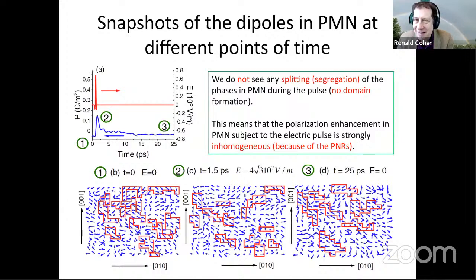Hi, Sergey. Nice talk. I wanted to ask you, your electric field is practically terahertz radiation. And so it must be somehow in resonance with the ferroelectric soft mode. Doesn't matter whether it is in PMN, NNO, or, as you mentioned at the beginning, in STO. In strontium titanate, this paper in Science shows that this effect is strong only if it is in resonance with this soft phonon, and if it is pumped at higher temperatures, when the terahertz radiation is out of the soft phonon, then this effect is not seen. So my question is, what is the difference between your hidden phase and the field-induced ferroelectric phase in strontium titanate or in PMN?